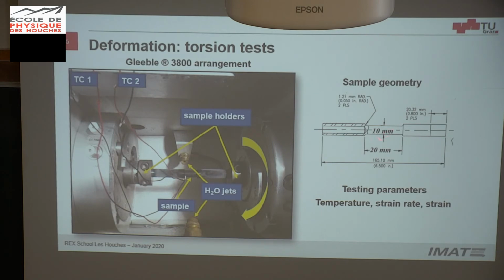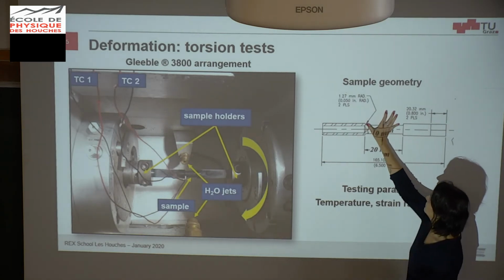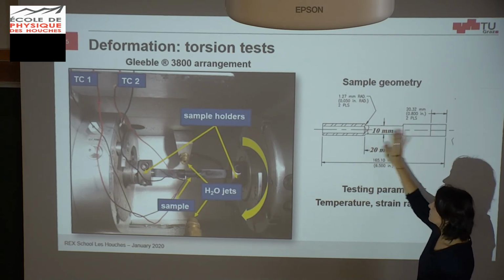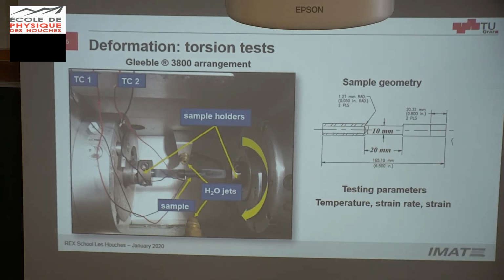No, it's only this part. If the sample is good, only this part is deforming, and this is not deforming. But of course, you may have some difference in temperature between this point and this point. What you don't want is a temperature gradient along the gauge. This is what you don't want. And then you have the water jets, which are positioned here. In our case, we also had to modify this a bit, because we saw that it was cooling down only from one side and not from the other.